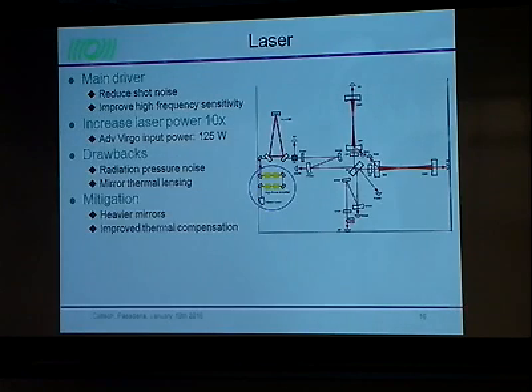So let me now move to the laser. In this case, the goal is to reduce the shot noise, improving the high frequency sensitivity, so increasing the power injected into the interferometer by about an order of magnitude, so move to 125 watt as input power. Of course, you have drawbacks like radiation pressure noise, mirror thermal lensing, and we have mitigation of this by using heavier mirror and improved thermal compensation.